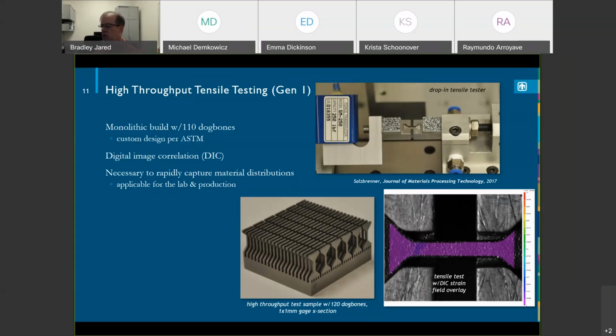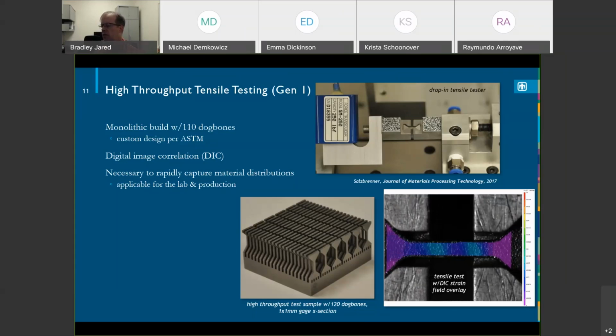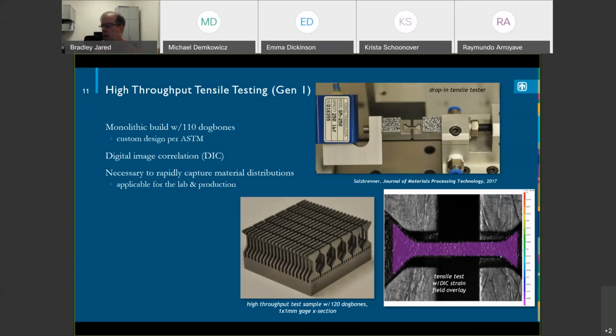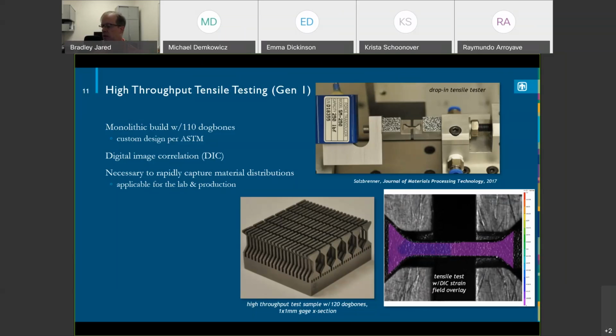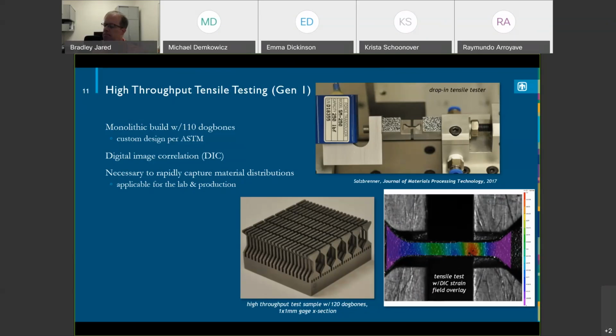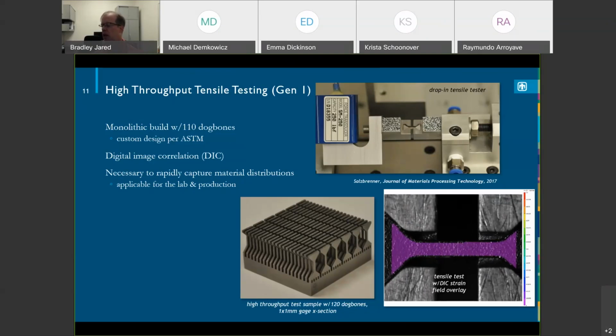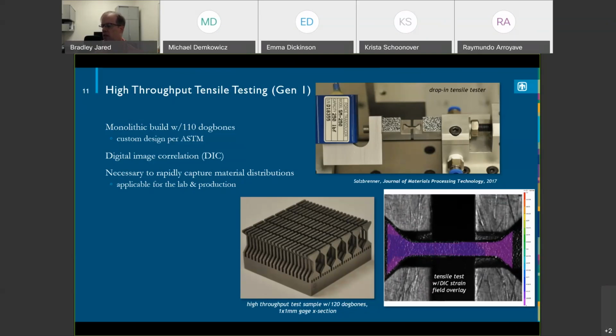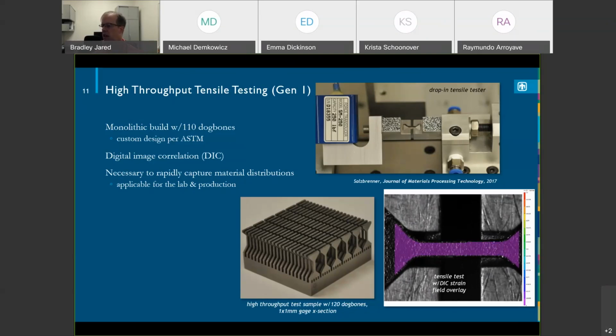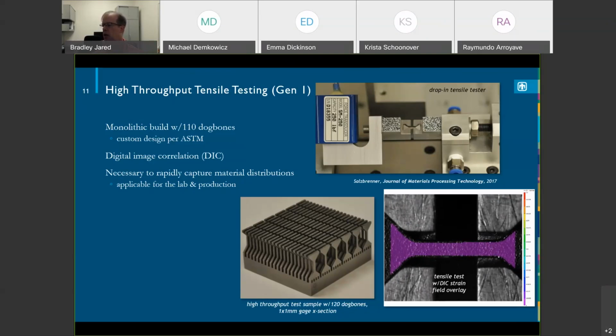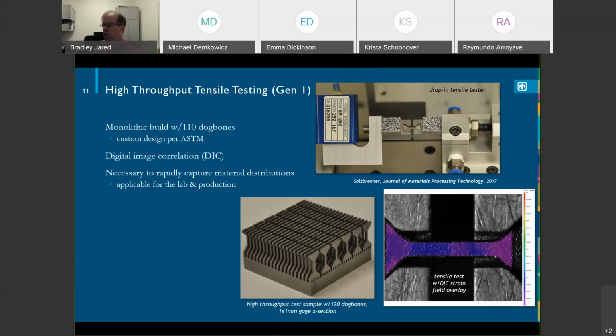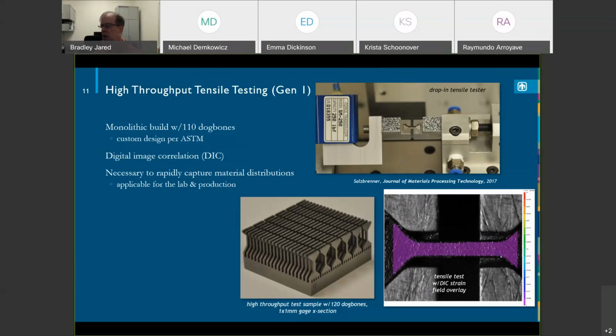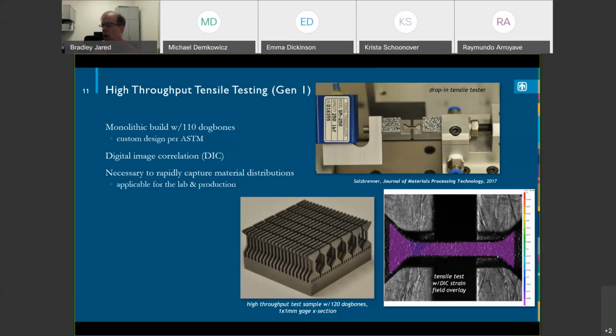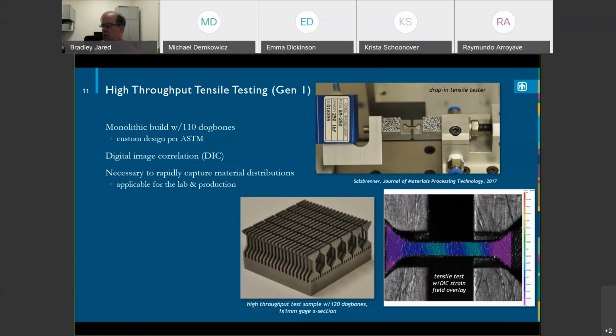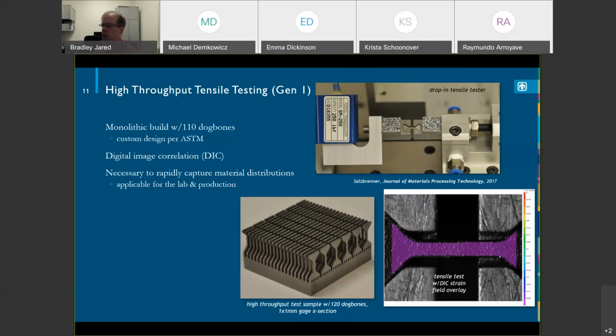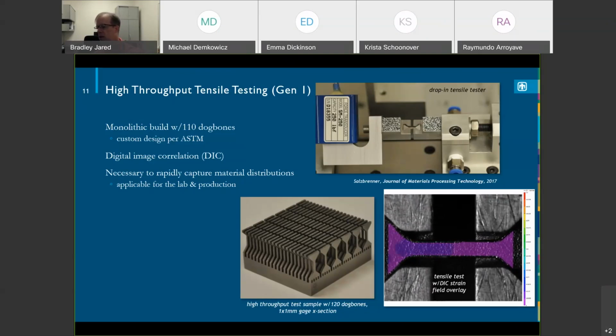So typically we use extensometers and things like that, fairly delicate, or at least intensive setups. And so a lot of times you'll get maybe 10 samples a day. 20 if you've got a technician that's fantastic and does a really good job. This actually allows us to do samples that are dropped in with some custom grips on a load frame, able to do these 10 an hour maybe or more. And we've actually been able to demonstrate more like one every minute or so, right? So this really changes the ability to capture large data sets.